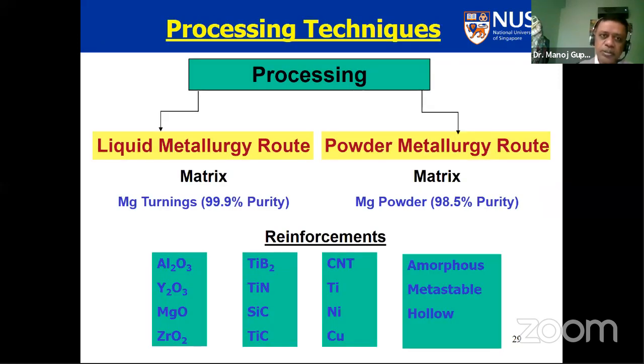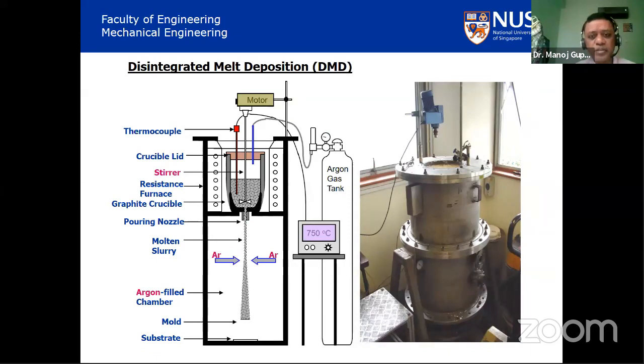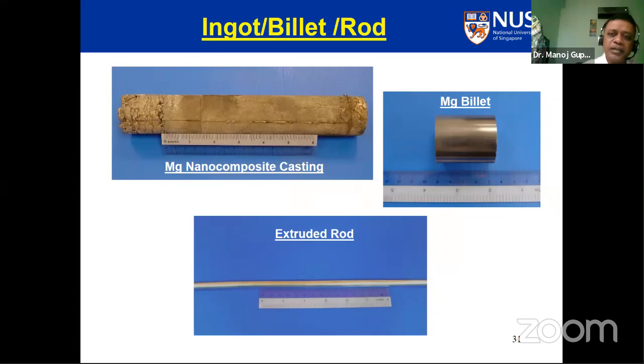These are the liquid-based methods and the powder-based methods. In the liquid-based method, we innovated way back in 1995, almost 25 years from now. This is called the disintegrated melt deposition technique, in which we just take the material in the crucible and heat it up to 750 degrees centigrade. We homogenize for temperature and particle reinforcement, bottom pour it, hit with argon gas jets, and we get an ingot. It's a technique which is not cost intensive, and it can be fabricated at a very low cost. So you can get the ingot and machine it.